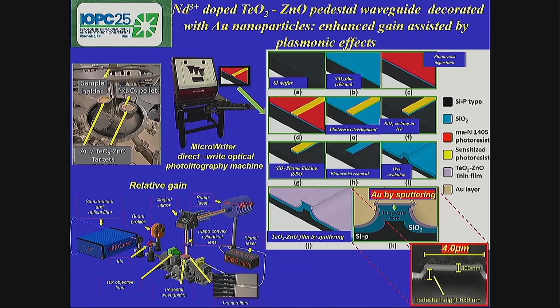The pattern is transferred to the photoresist by a laser that operates at about 385 nanometers. By using this new technology, we prepared neodymium-doped tellurite thin films decorated with gold nanoparticles with the intention to see the plasmonic effects on the optical performance of the waveguide. Here I show you the setup used in our chamber. In one of the electrodes, we place the target of the host, with a pellet of neodymium on it, and on the other electrode, the target of gold. It's a commercial one with high purity. The last step in this case is not the core, but the deposition of the gold, also by sputtering.